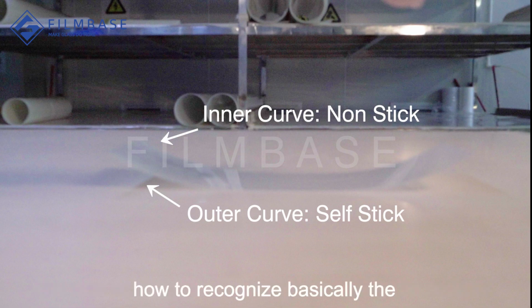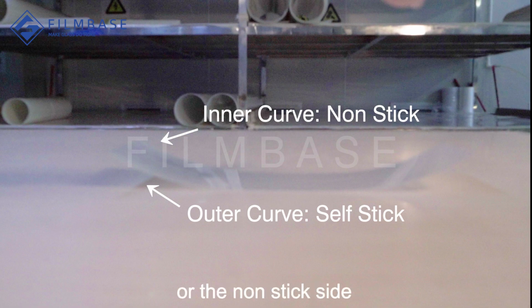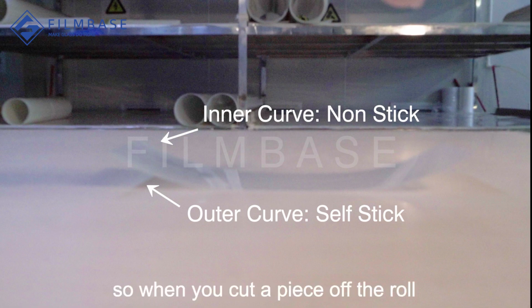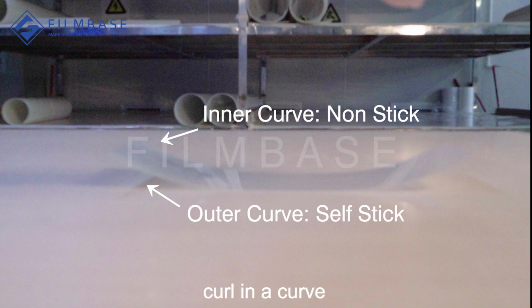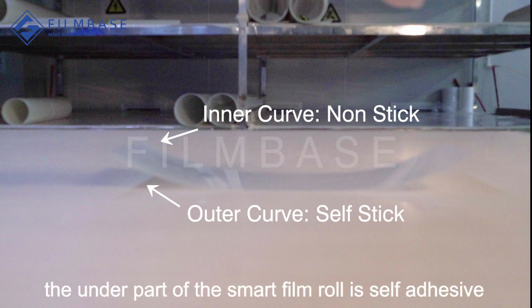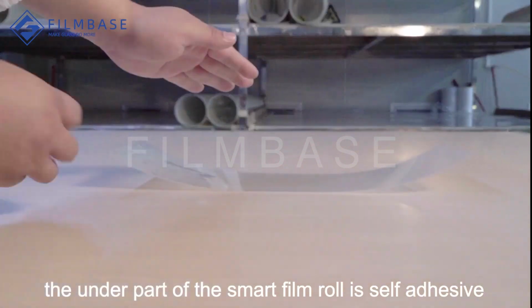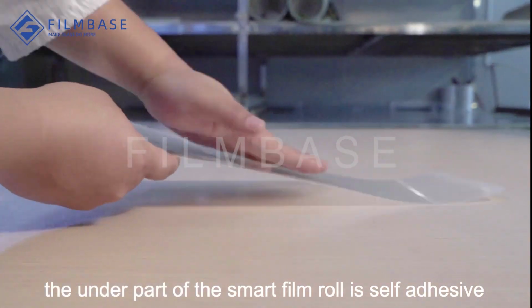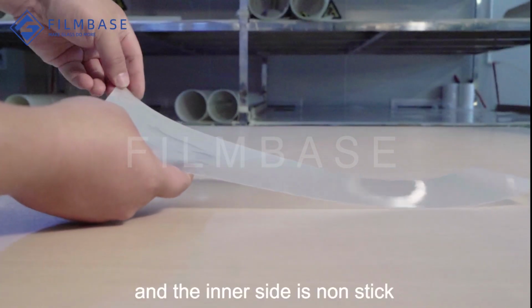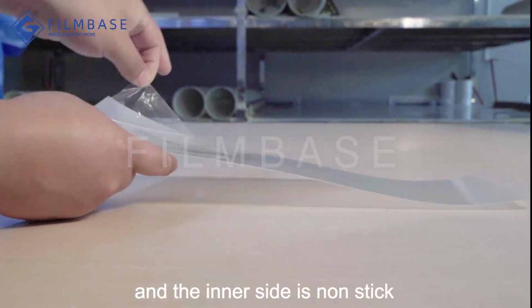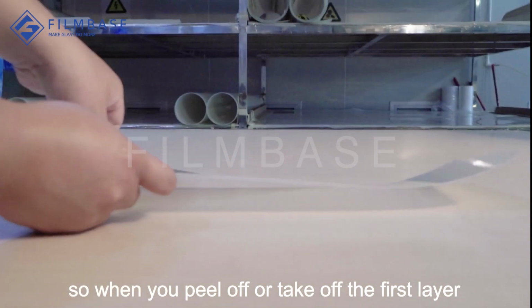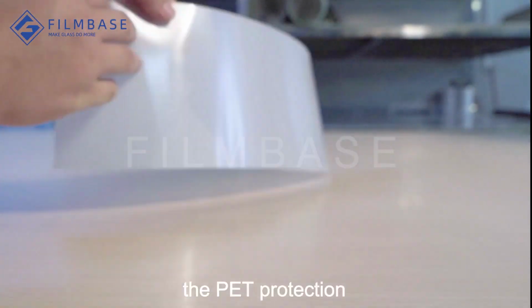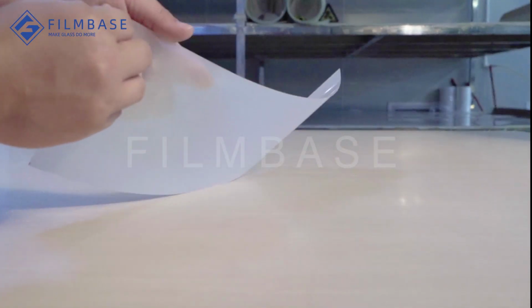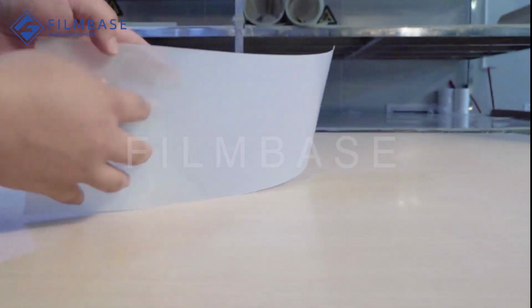How to recognize the self-adhesive side or the non-stick side. When you cut a piece of the roll, the smart film will always curl in a curve. The outer curve side, or the under part of the smart film roll, is self-adhesive or self-stick, and the inner side is non-stick. When you peel off the first layer, the PET protection film, you can feel if it's sticky or not.